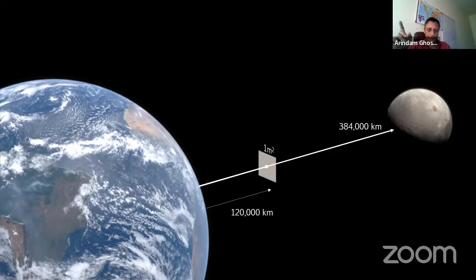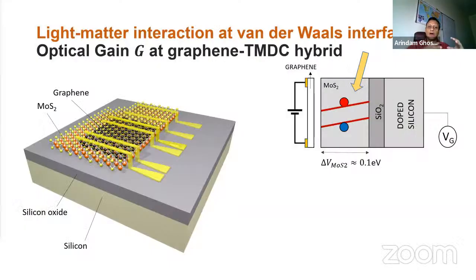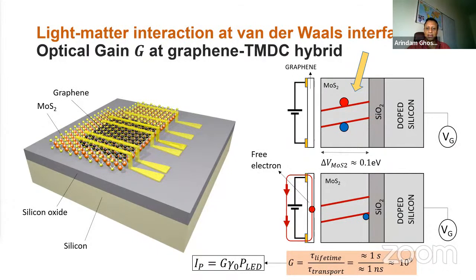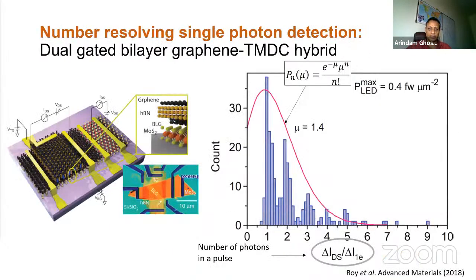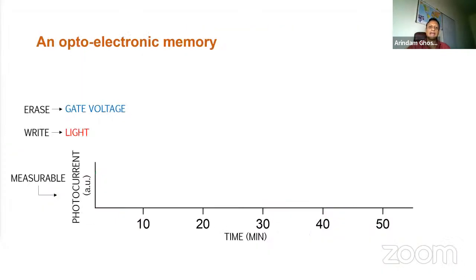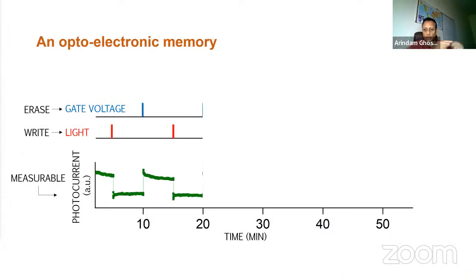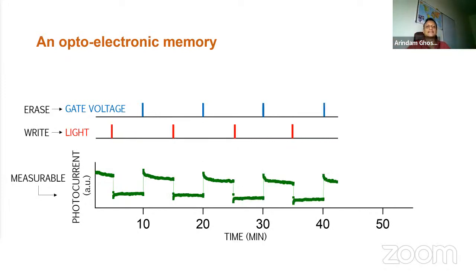You see, neither graphene nor molybdenum disulfide are such sensitive detectors. We could get this detector because we have now mixed and merged 2 different elements and pulled out the best of these 2. Here what happens is that light comes, it forms an electron-hole pair in the molybdenum disulfide layer. The electron then goes into graphene and moves around, and it gives you a large optical gain, which leads to an extremely high sensitivity to optics. Of course, later we made various electronic devices like single photon detectors and a memory device in which you use a pulse of light to write and a gate voltage to erase, and you can go on and on as an optoelectronic memory, or very sensitive optoelectronic memory.